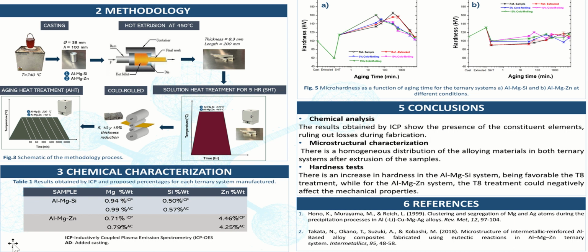After obtaining the samples, we proceed to their characterization. A chemical analysis was carried out on the samples obtained to verify if the constituent materials of the ternary systems were present or if any of them, such as zinc, which has a lower boiling point than aluminum and magnesium, were lost during casting. In Table 1 we can observe the results obtained by ICP and the values added at the time of fabrication of the samples. The results tell us that the fabrication of the samples was successful.